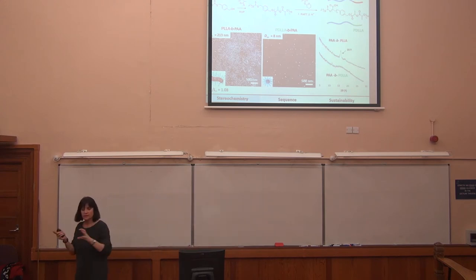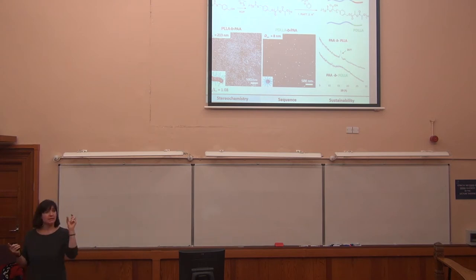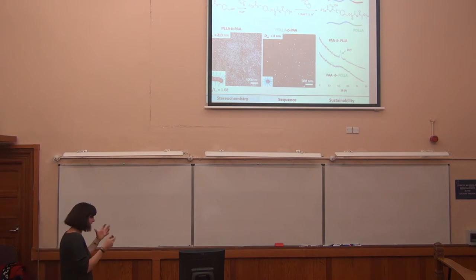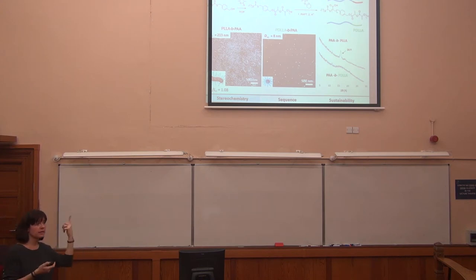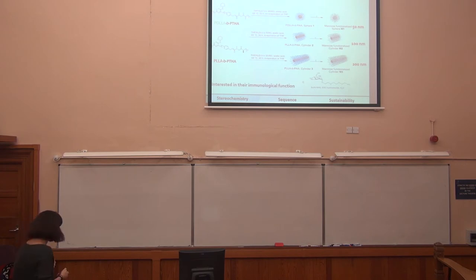We move out of that predicted regime and into this regime where we make anisotropic structures and these worm-like structures. And we can confirm the reason why we get these cylinders is actually because of crystallization of the core, and we do that using just wide-angle X-ray scattering. But this is chemically the same. The arrangement of whether we have either a random coil or a helix leads us to forming a different hierarchical assembly. And how might we use that?